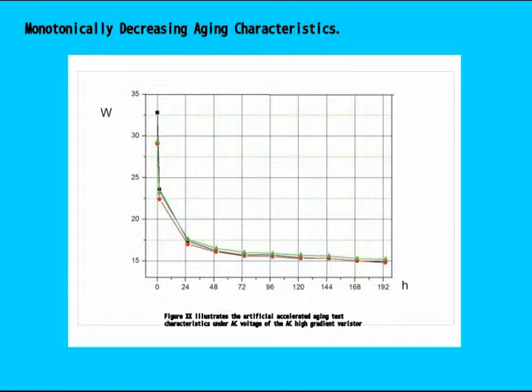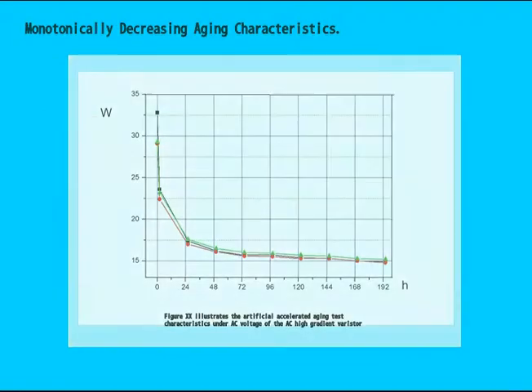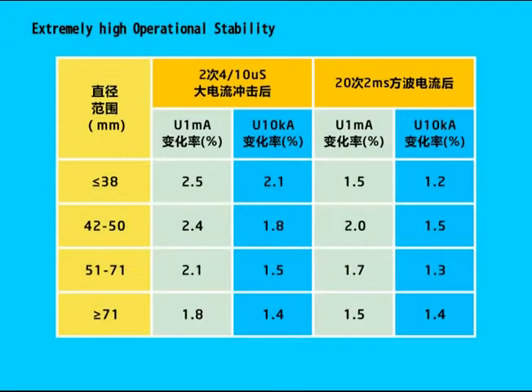The above three aging curves demonstrated that the TGE varistors has excellent aging performance, extremely high operational stability. As shown in the table, after sustained high current impulse at specified amplitude or rectangular impulse, the change rate of both the residual voltage and the reference voltage of the TGE varistor are small. This can ensure the overall operational status of the varistor to remain basically unchanged after the arrestor action.